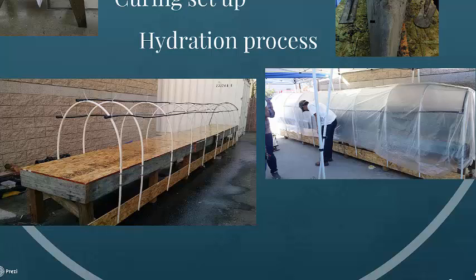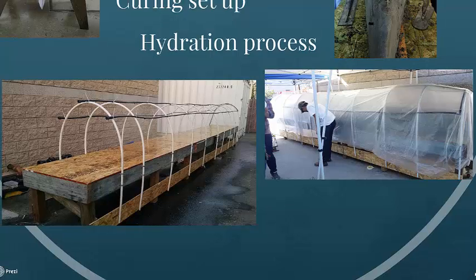The curing process involved a 20 psi regulator and 40 360-degree misters that overlapped with each other 6 inches for a spraying capability of 22.5 feet. A timer was set on the hose bib and set to spray 4 times a day for 3 minutes each. The canoe was demolded 9 days later. Finished patching and light sanding achieved a finished canoe. Our challenges this year were to build a monolithic 0.2 inch thick canoe that was seaworthy.